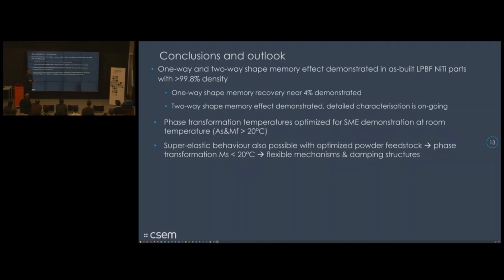So if we have a different reference temperature, we can use also the same, or a powder feedstock with different content of nickel can be used for phase transformation below martensite start below 20 degrees. And we can use this for flexible, again, flexible mechanisms. So where we have large angle flexible pivot, we can imagine even larger angles using a similar design, or for damping structures is also very interesting, as it was already mentioned.